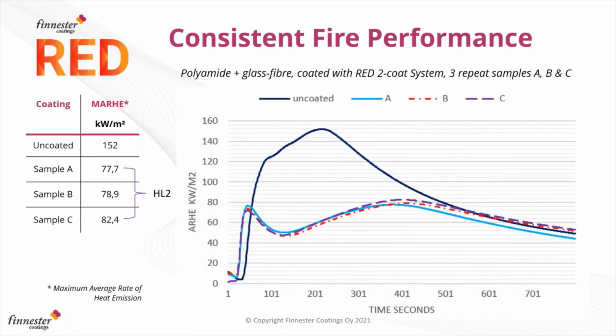Here we have measured the heat release from the standard glass fiber polyamide substrate, and without any coatings, you can see that the heat release is 152, but when you add a coating to that, you can halve that, and you have the same results with the 3 different samples, very consistent results.